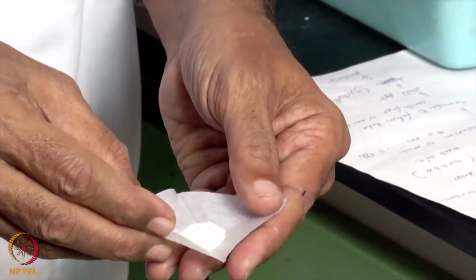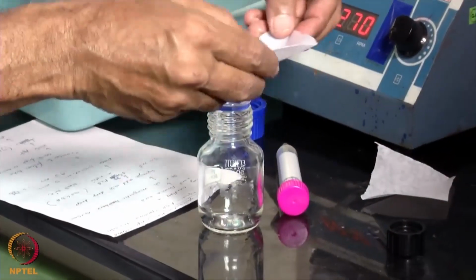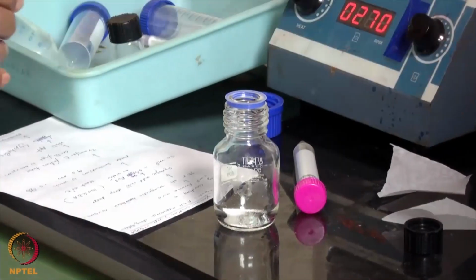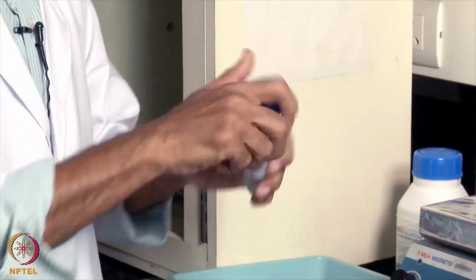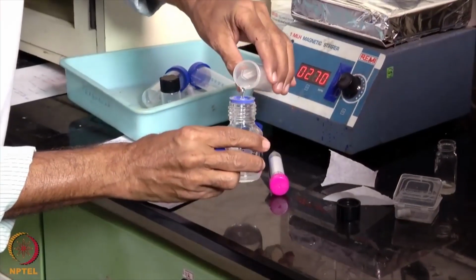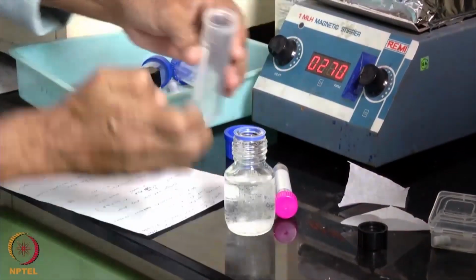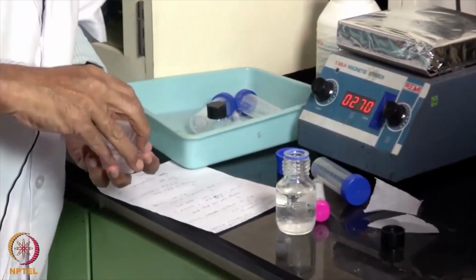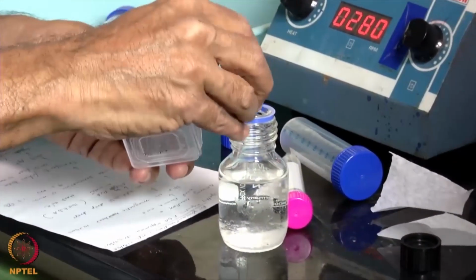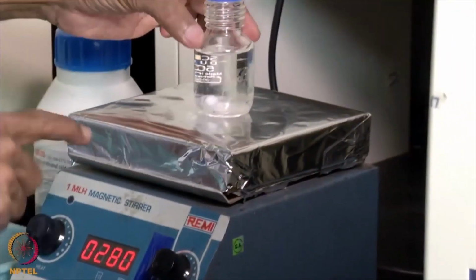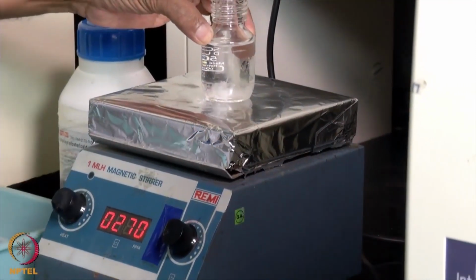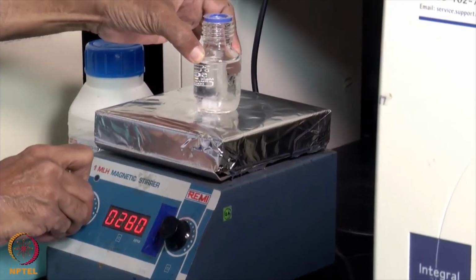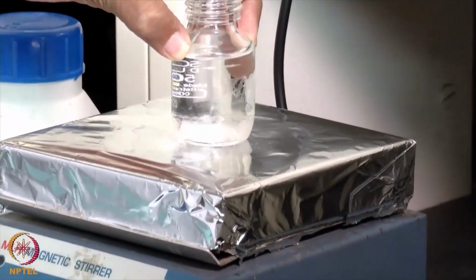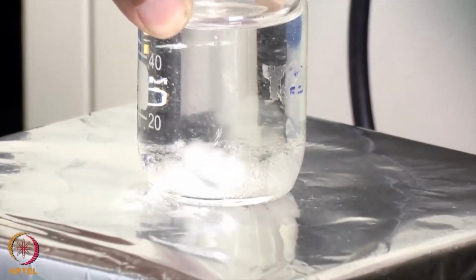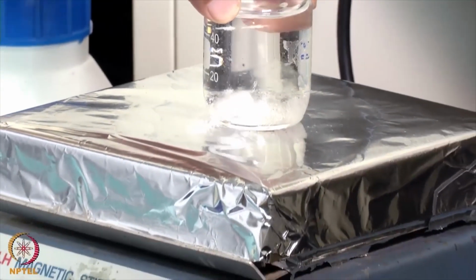and then 0.5 grams of PVA I take. And I take 50 ml of water. I again stir it, but here I have to heat it to 50 degrees centigrade. Okay, so for another 5 to 10 minutes. So I set the temperature. Because PVA is not soluble in cold water, so we are heating it to 50 degrees centigrade.